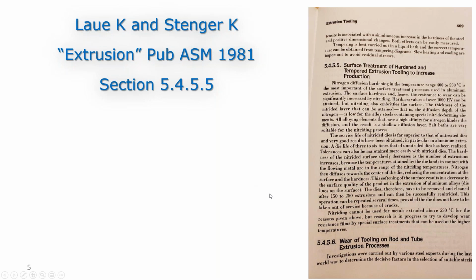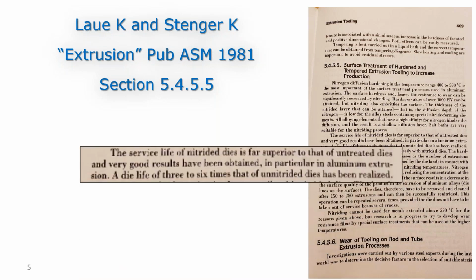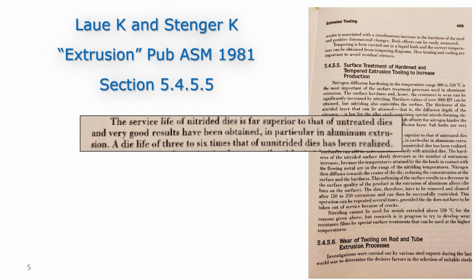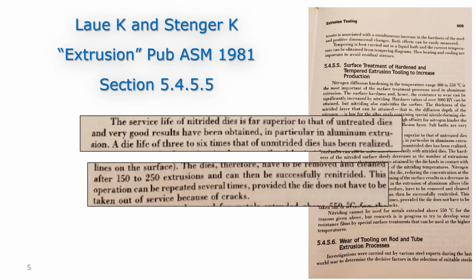Just a little bit of history. I always like to dig back. My favorite book is Lau and Stenger, Extrusion, published by ASM in 1981. Section 5.4.5.5 is on surface treatment for tools. And the first bit is: the service life of nitrided dies is far superior to that of untreated dies, and very good results have been obtained, in particular in aluminum extrusion. A die life of 3 to 6 times that of the un-nitrided die has been realized. So that's 1981, we knew that.